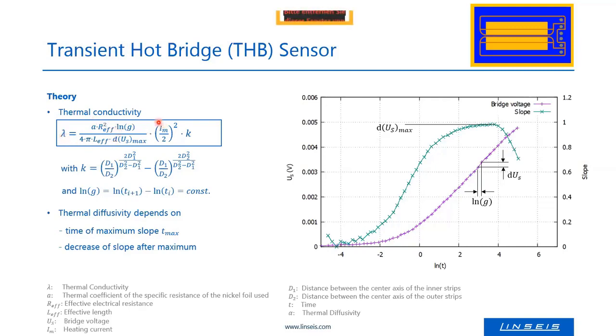Here we have the heating current. Of course the curve also depends on the heating current which we apply and on the thermal conductivity. Everything else is constant. These factors here are constant, the calibration constant is constant, and the current is also constant during the measurement. So we only need to calculate the slope and then we can calculate the thermal conductivity.